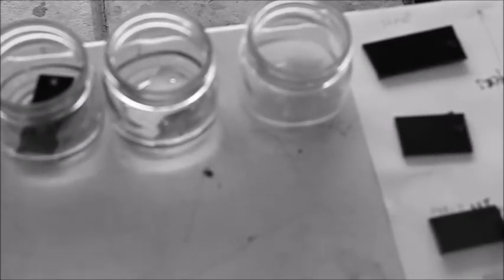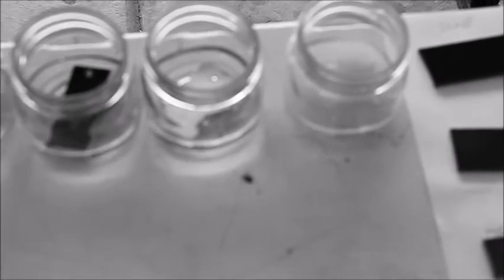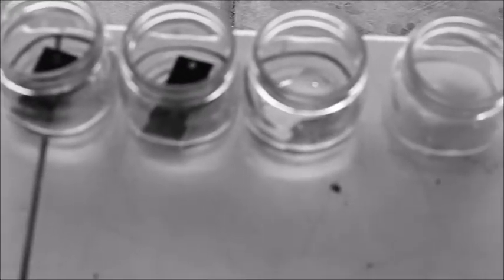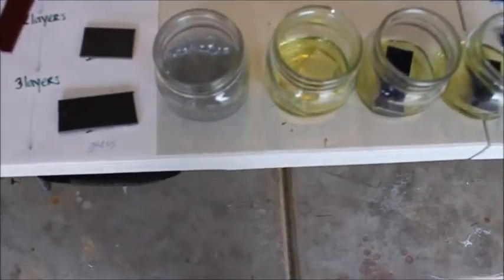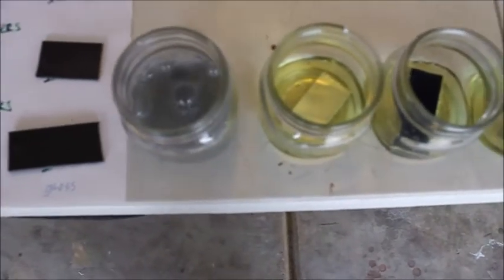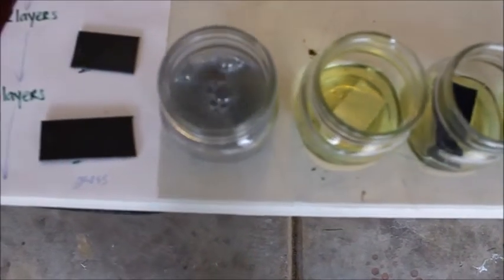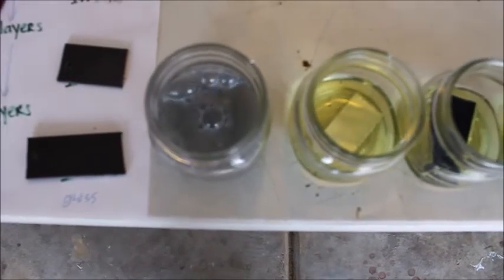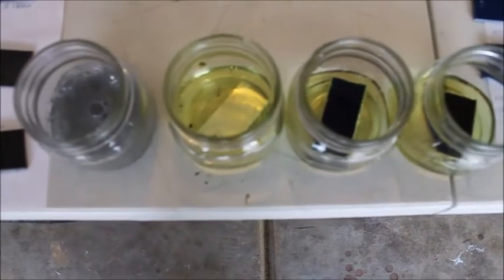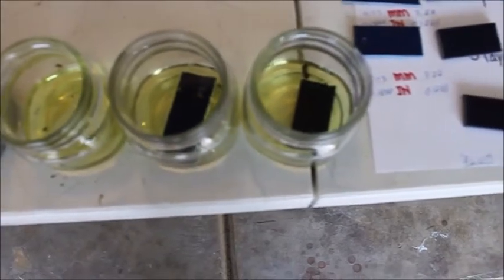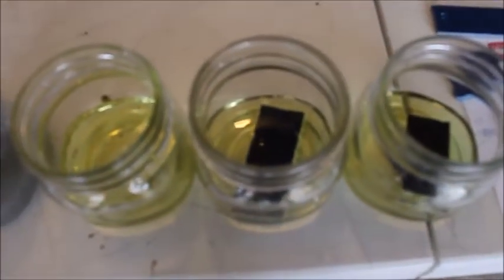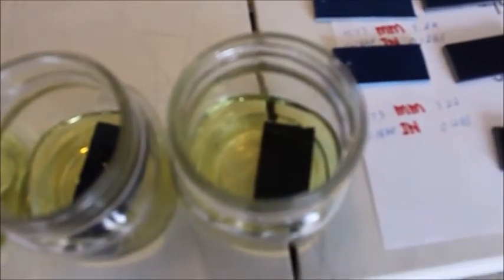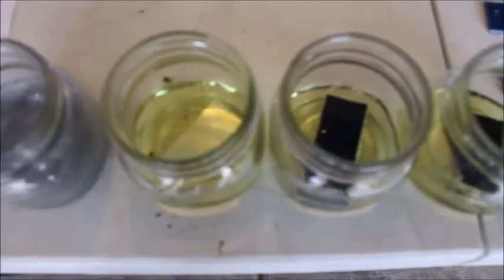Notice the bubbling of the regular aluminum and no chemical reactions with the others. Okay, ladies and gentlemen, as you can now see, we are over 5 minutes in, and the regular uncoated steel is already completely bubbling and melting away with a chemical reaction. Yet our nano-coated pieces still show no signs of chemical wear or resistance. The coated metal, the blue-coated nanometal, and the black matte-coated nanometal still show no signs of chemical corrosion.